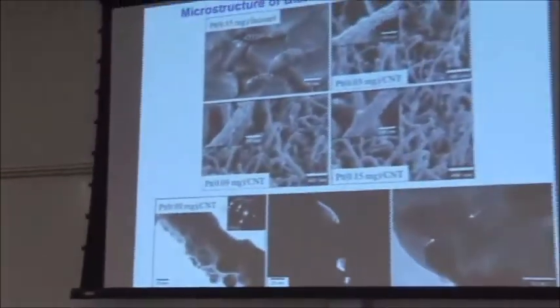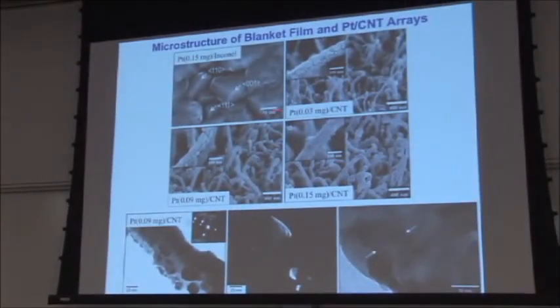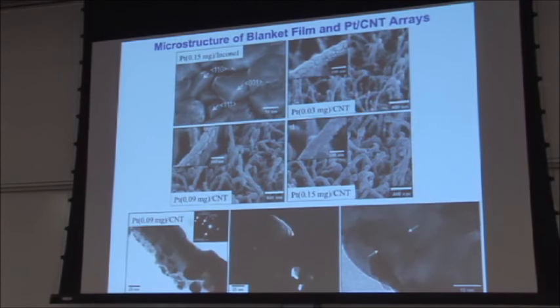So these are what the as-grown carbon nanotubes look like. It was about 5% amorphous carbon and maybe 3% catalyst. So when we deposited the platinum on an Inconel support, it's still really nano by definition of nano, since these are all less than 100 nanometers.